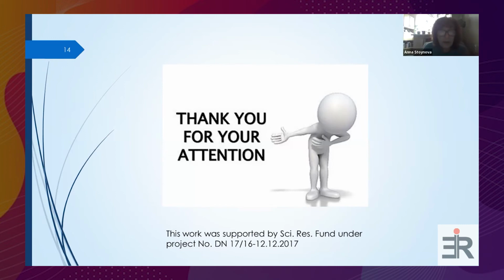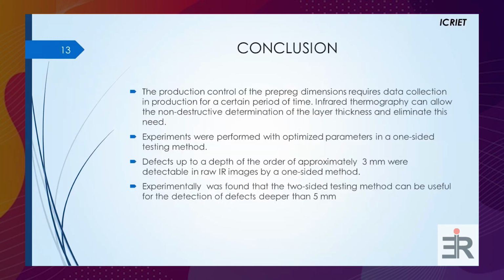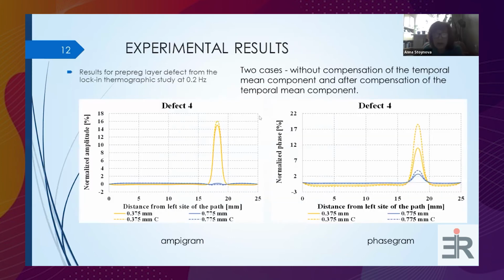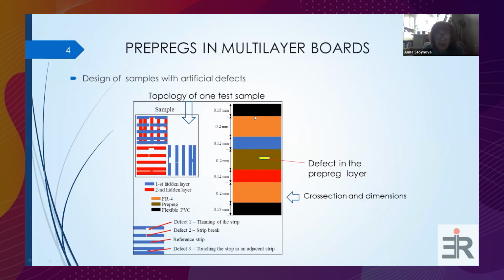Yes. After simulation by using infrared thermography, we simulated using pulse thermography, but the results were not good. We couldn't see defects in the prepreg layer. But when we use optical lock-in thermography, we can see them.